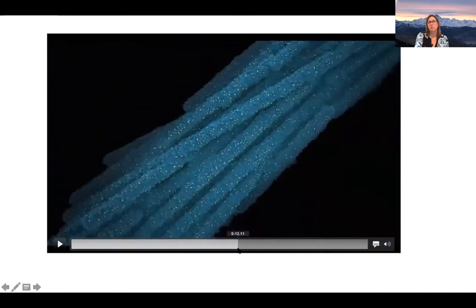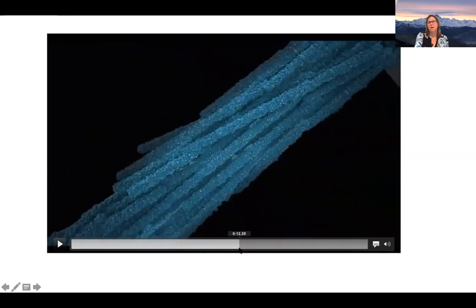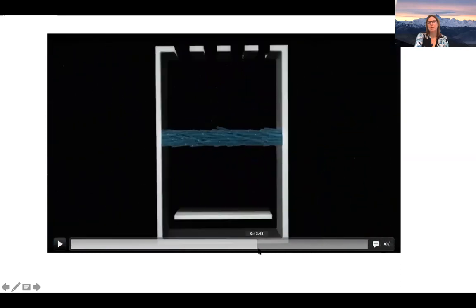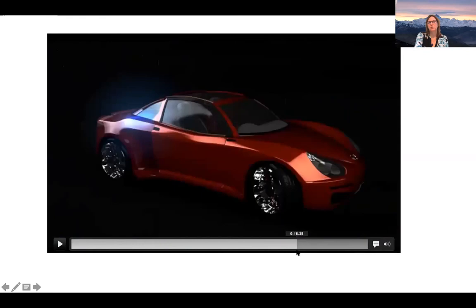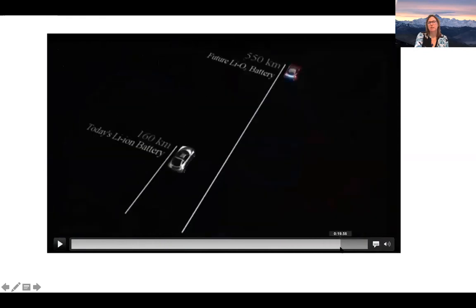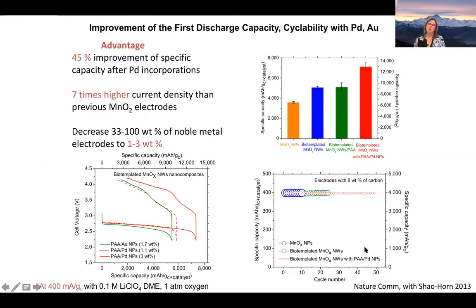And so we were able to do that by structuring the material, giving it this spiky structure, the combination of materials. And the idea was to eventually be able to increase the distance between charging. And so we did that by making these two components mixed together. We had 45% improvement in the specific capacity, 7 times higher current density. And importantly, what we did was decrease the amount of noble metal, because obviously you're not going to want to have a lot of expensive metals in your battery electrode material.